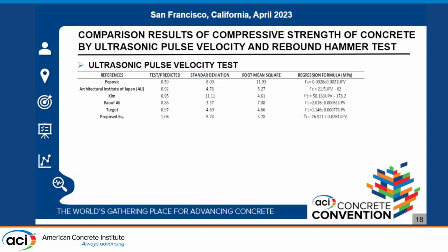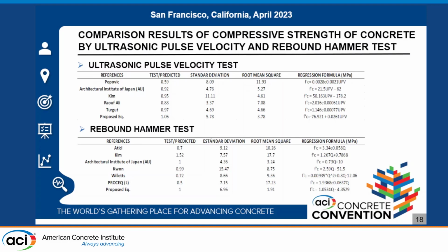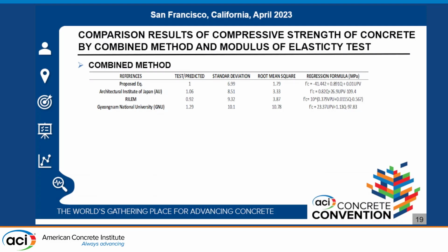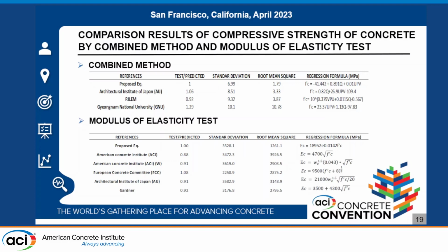These parameters are the test prediction ratio, the standard deviation, and the root mean square. In the second table, we have models that are related to the hammer test. We also found combined methods developed around the world that have very good parameters. And finally, we could also find other models that have a very good correlation coefficient and very good parameters also. Two of them are from the American Concrete Institute.